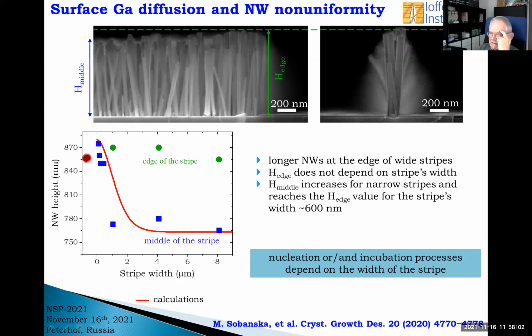Moreover, what we notice is that this inhomogeneity of nanowire length strongly depends on the width of the stripe. So if we measure here the edge, it doesn't matter too much how narrow the stripe is. We start from 0 up to 8 micrometers, more or less.